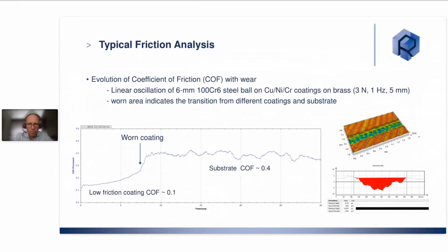In fact, the big interest of this combination and the typical friction analysis that we may do with our instrument is in fact to record the coefficient of friction as a function of cycle or time, and see on a specific example on a coating where the coating might be breaking, what would be the wear time of this material, and then with the 3D profilometer being able to observe the 3D deformation on a very precise level on different locations on the sample.